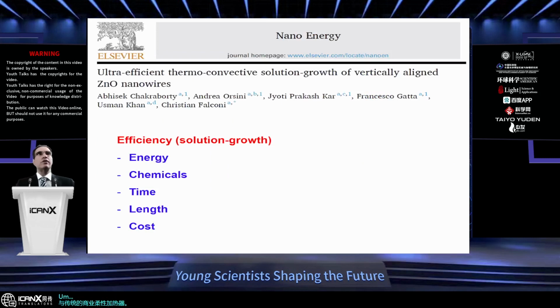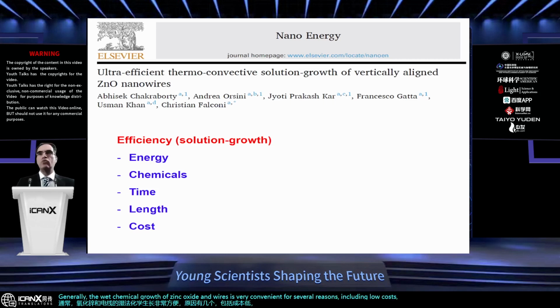And this is another work where we also wanted to take advantage of electronics for growing nanowires. And we noted that generally the wet chemical growth of zinc oxide nanowires is very convenient for several reasons, including low cost, simplicity, possibility to grow on large area on flexible substrates. But there are some problems with efficiency: in terms of energy, chemicals, time, length, only short nanowires can be grown, and also cost in terms of reagents.